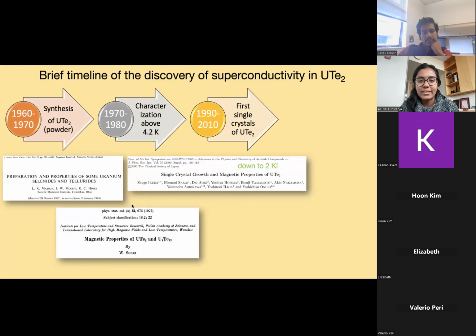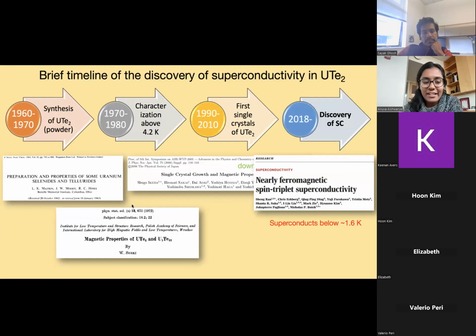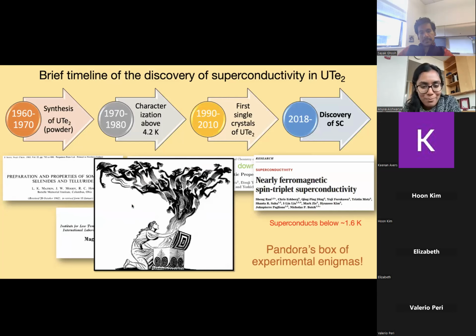However, it was only in 2018 that Sheng Ran and colleagues synthesized this material and cooled it down to very low temperatures, and discovered superconductivity. This probably has to do with both technological advancement and perfecting the growth recipe and the stoichiometry of uranium and tellurium, which seems to be important in this material. Anyway, after 2018, the discovery of superconductivity in this material opened a Pandora's box of experimental enigmas that I'll briefly go over.